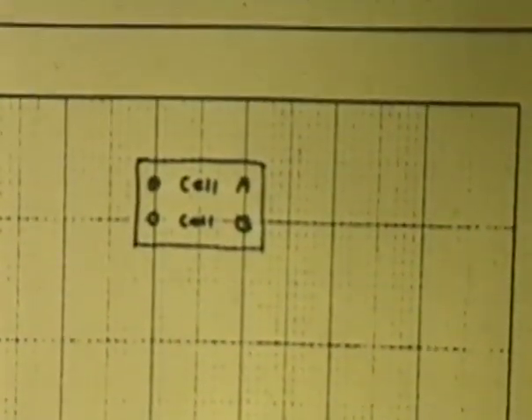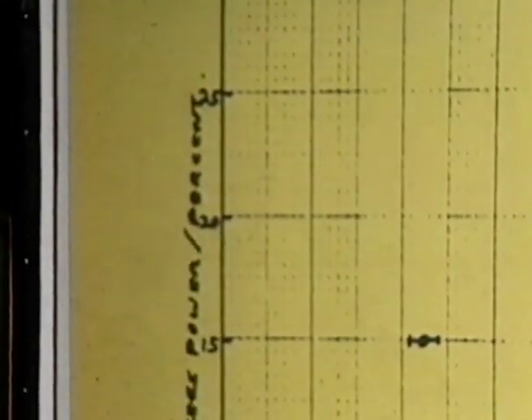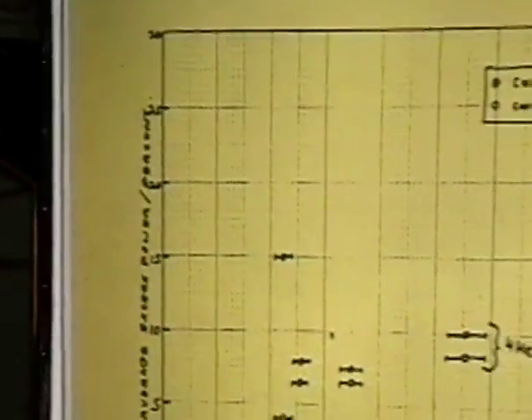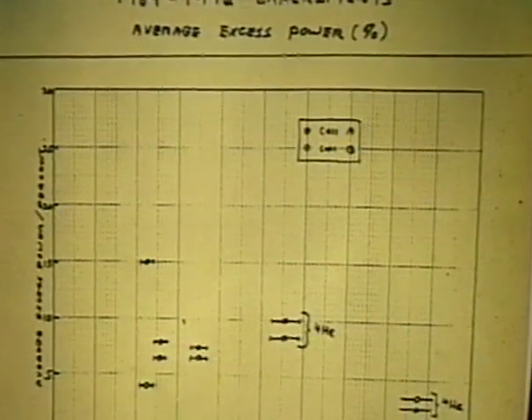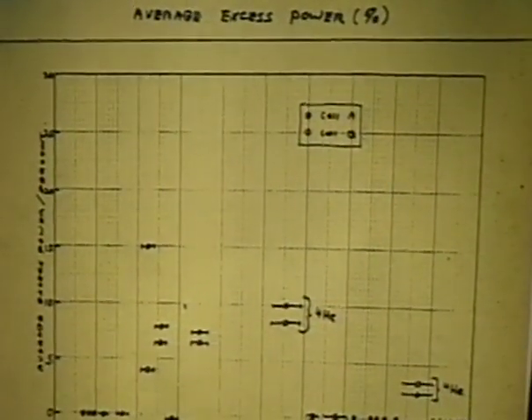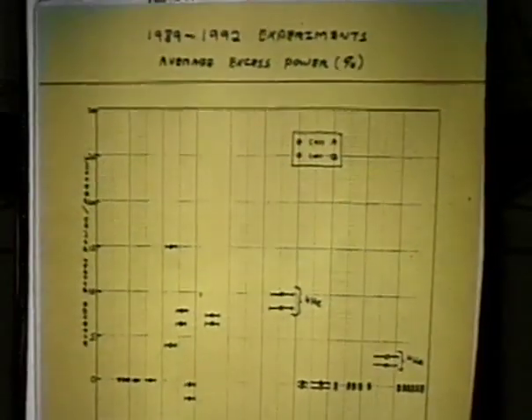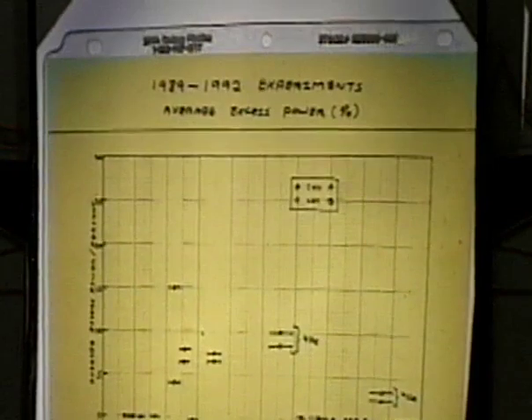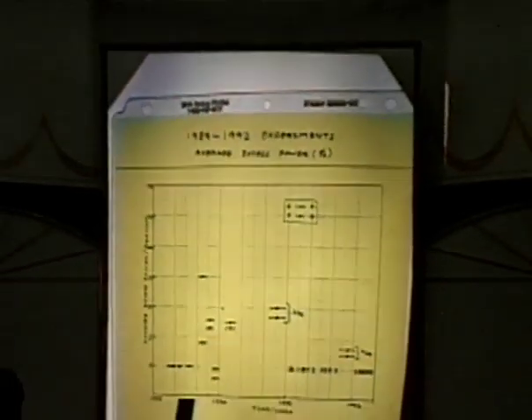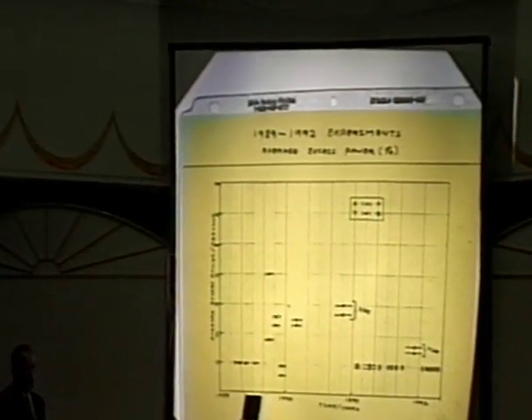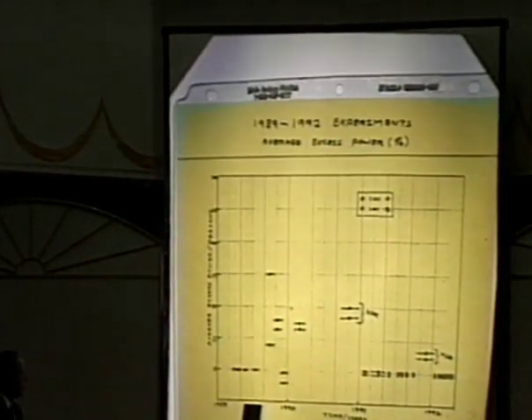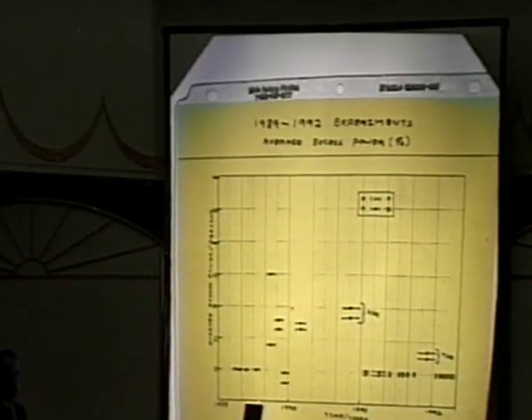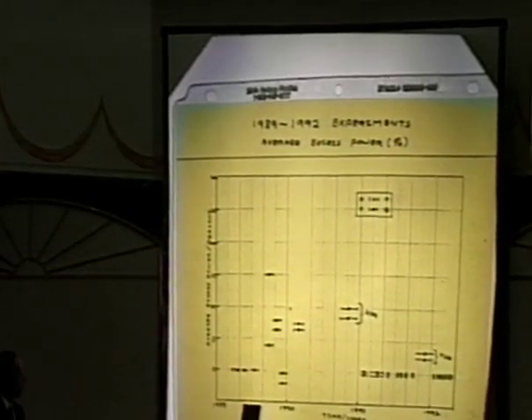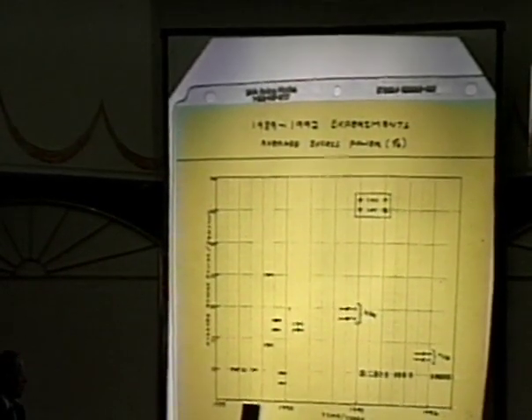Then we didn't run any experiments for a period in here, and then towards the end of 1991, we wanted to test for helium. This is our first test of helium, and those experiments averaged excess heat, and we found helium-4 in the gases coming off. You may wonder why we didn't make much progress for a long time after that, and this is why. For almost a year, we never had excess heat again. You see all these experiments. There's a lot more than we show here. I don't want to keep putting dots up there, but roughly we ran experiments for a full year and never saw excess heat. And finally, towards the end of 1992, we found excess heat again.